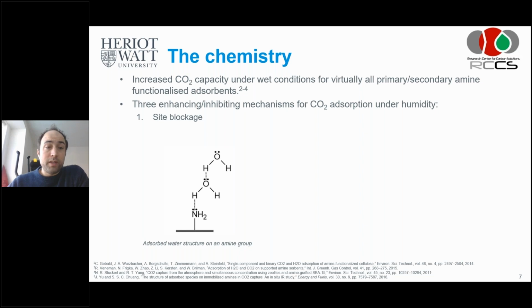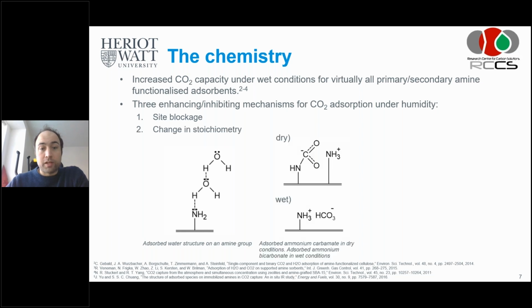So we said one of the effects or mechanisms is an inhibiting effect. If you have an amino group that is grafted or tethered to whatever kind of solid surface you have, then water will simply hydrogen bond to that amino group, right? So you'll get layers of water, and that basically takes away that amino group from the CO2 because it's taken up by water. CO2 will bond much stronger to the amino group, but it will be more difficult to reach it. So there will be some sort of site blockage effect there.